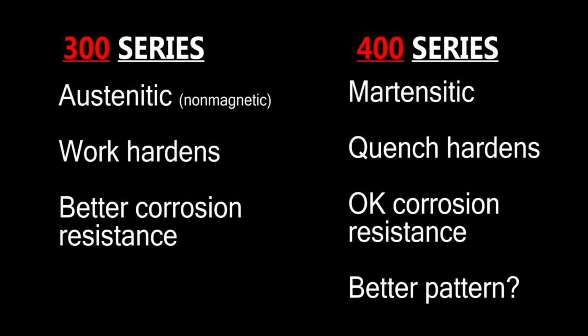There are 5 classes of stainless steel. We usually choose from 300 or 400 for stainless sandwich. The 300 series steels are austenite at room temperature. They're austenitic. They are not hardenable by heat treating for this reason, but they can be hardened to some degree with cold working. But they can't be hardened enough to make a knife. So the 300 series is non-magnetic, more ductile than the 400 series, and more corrosion resistant than the 400 series.